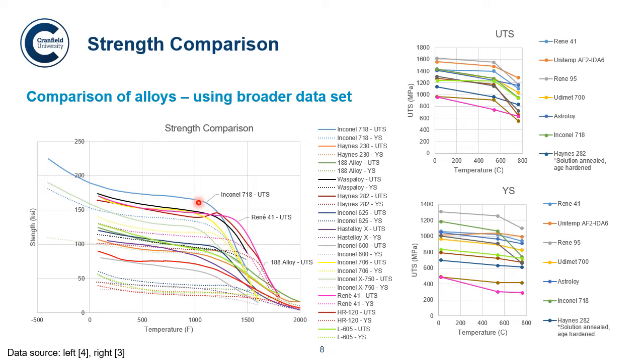So the top alloy that actually comes out is Inconel 718. It's at intermediate temperature ranges, and as we get into the increasing temperature ranges, we start to see 718 drops off, and Rene 41 kind of takes over from there. And then as you get even higher in temperature ranges, so now looking at 1700 Fahrenheit, alloy 188 will start to take over from Rene 41 as the leading alloy, which you can see right at the end here.